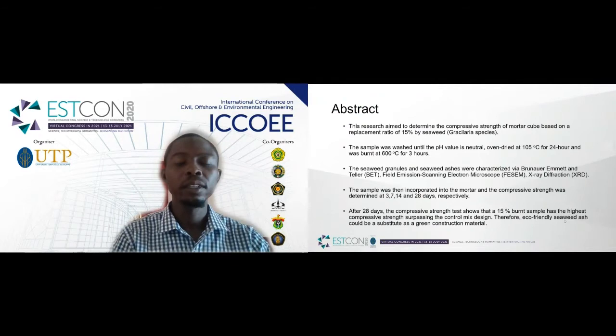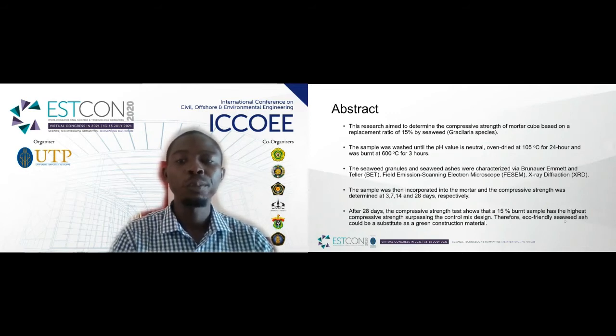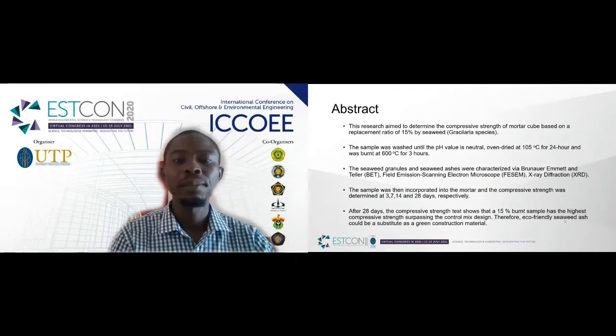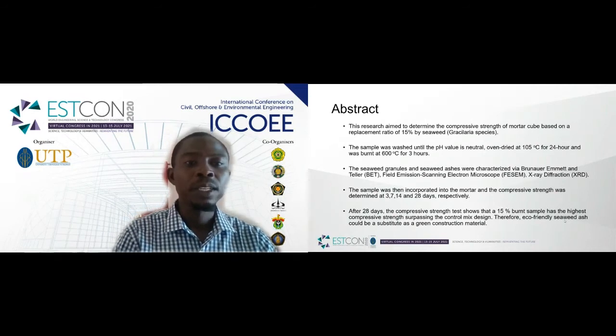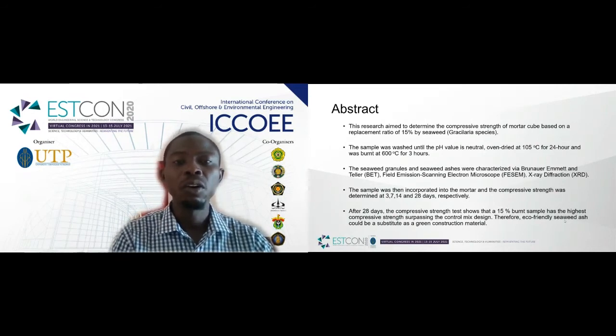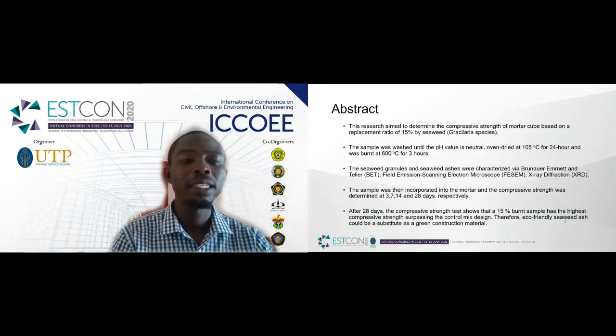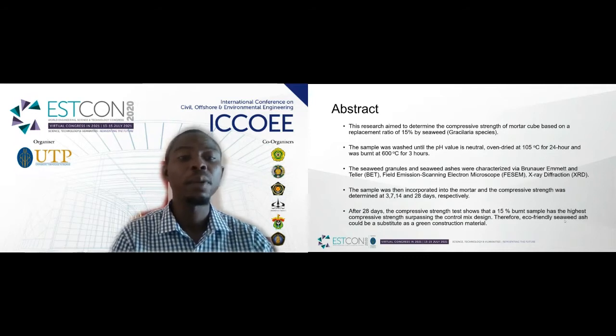The abstract. This study aimed to investigate the compressive strengths of mortar cube based on percentage replacement level from 0 up to 15% to replace cement by seaweed ash. The sample was washed until the pH value was neutralized, then oven dried at 105 degrees C for 24 hours, and later it was burnt at 600 degrees C for 3 hours in a muffle furnace.